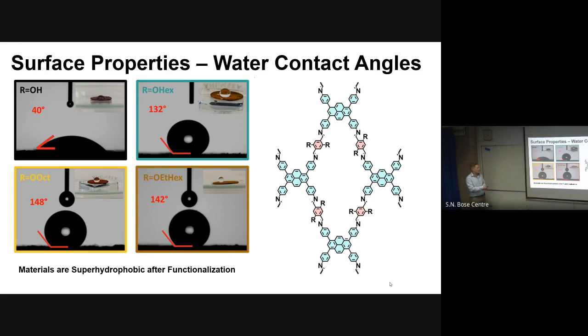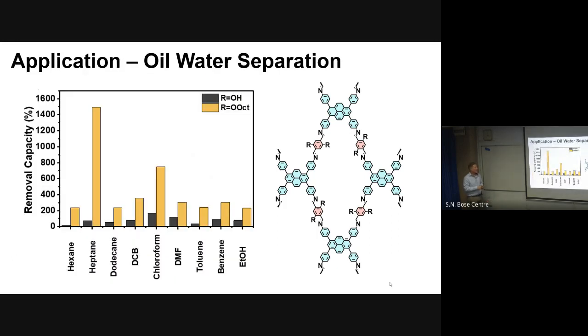But still, we see the general trend that when we have the side chains attached, the materials will repel water quite easily, and they soak up heptanes, hexanes. I don't show the data here quite well. And if we have only the hydroxy groups, the water will get soaked. So one potential application that we thought about is the water separation. We essentially soak these materials with different solvents from the lab. They don't take up any water apart from the non-functionalized material.